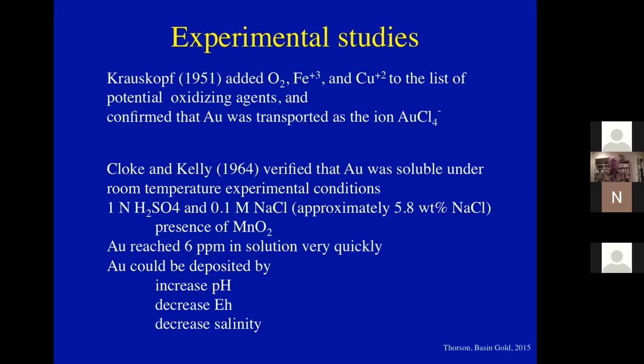Krauskopf added some more data to this, where he added oxygen, iron +3 and copper +2 to the list of potential oxidizing agents. And he confirmed that gold was transported as the ion AuCl4 with a single negative charge. And Cloke and Kelly verified that gold was soluble under room temperature experimental conditions in 1 normal sulfuric acid, 0.1 molar sodium chloride, approximately 6 weight percent sodium chloride, in the presence of manganese oxide. Under those conditions, gold reached 6 ppm in solution very quickly. And the gold could be deposited by an increase in pH, a decrease in Eh, or a decrease in salinity.